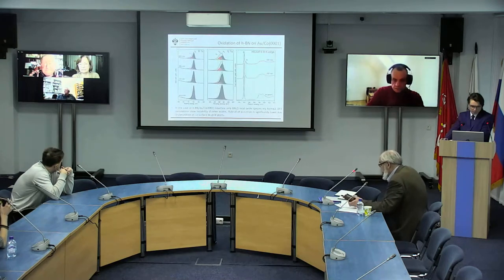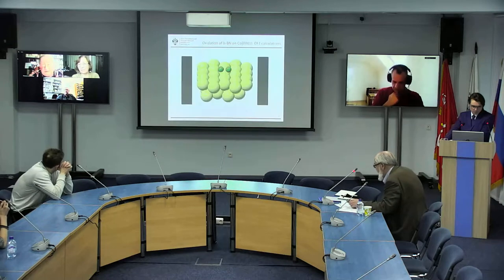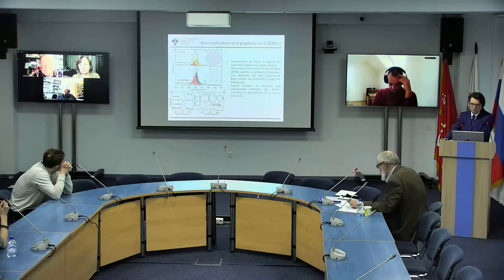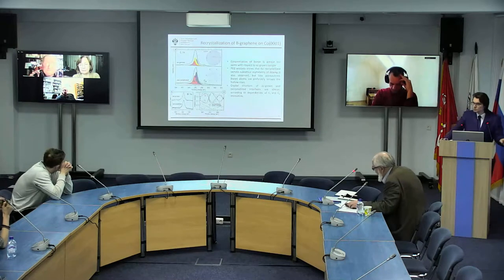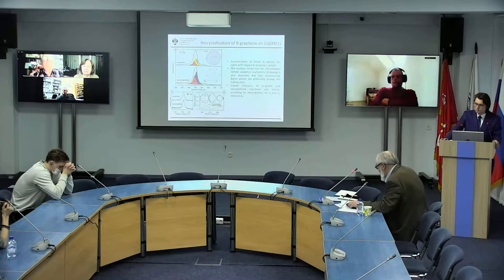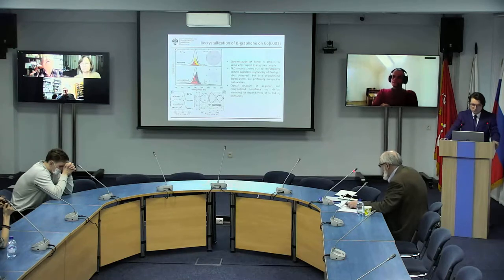On image 3.7 in chapter 3, you have the boron 1s photoelectron spectrum, and the line is divided into two components, and the intensity of these components oscillates. And on this image 3.7, you give this oscillating curve that you obtained during this breakdown. And here you should take into account the fact that this breakdown can be approximated, because the use of a fold of one Lorentz and one Gauss is not enough for a specific description, because the line does not take into account the spread of electron density of photoelectrons. They are described as plane waves. And in this case, such oscillations can be just the result of a certain approximation of this expansion.